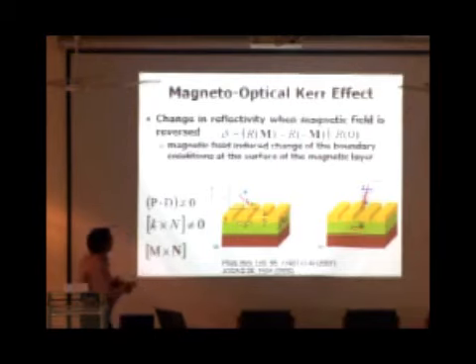For example, in this case, what we studied is the magneto-optical Kerr effect. The idea is you have the substrate on which you have a magnetic material, in this case bismuth, yttrium, iron garnet, on top of which we have the metal gratings.